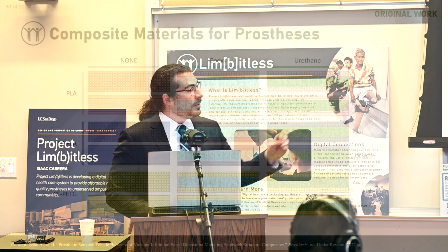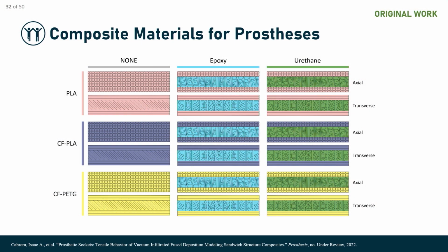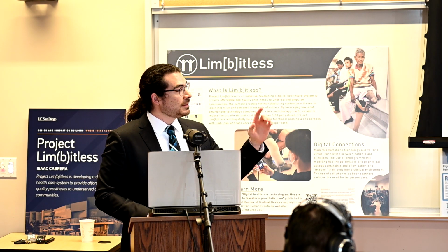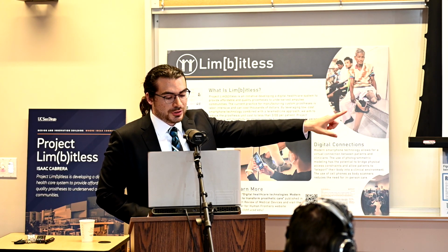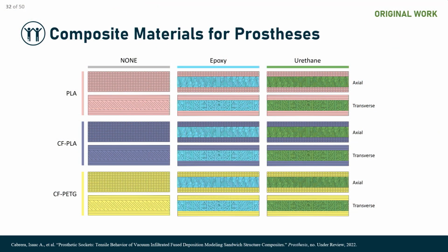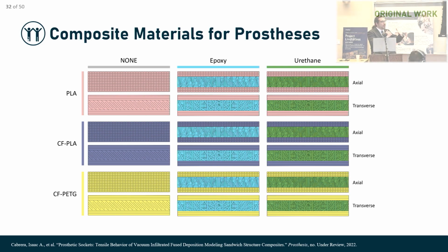And so my team and I tested out 18 different material matrix print combinations where we evaluated the materials themselves, looking at different loading configurations for axial and transverse loading, and then of course the materials plus the different epoxies and the different urethanes. So we had 18 different composite materials, and you can notice here that these are all sandwich structures. Meaning that you have our face sheets, which in our case are our filaments, and a separate core. And our core material is the resin that we infiltrated it with.